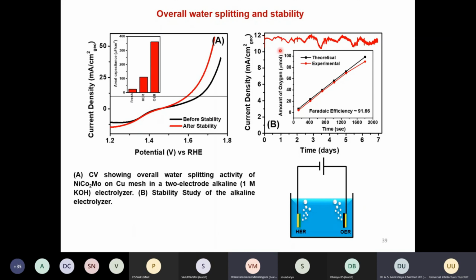We have also studied the stability over long durations, for example, 7 days. Generally people do 24 or 48 hour studies, but in this case we did very long-term stability studies for 7 days, and what we found is that after the precondition, the catalyst is very stable. We have also measured the theoretical and experimental Faradaic efficiency. We compared them and found almost 90% efficiency for the oxygen evolution reaction.